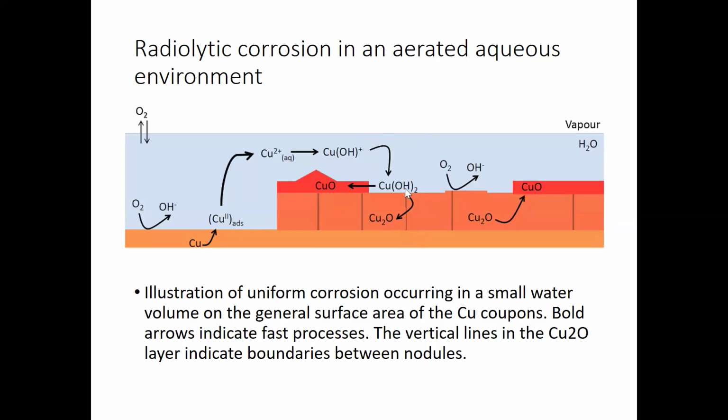From this point, you can have a buildup of copper oxide, so Cu2O. You may get small amounts of the CuO buildup on the surface, so it'll maintain a 2+ state, or it can go down to a 1+ state, depending on what's happening redox wise. And then you can also have oxygen at this point itself being reduced. So this is another possibility here, and that can then lead to buildup of more copper oxide on the surface of these corrosion products.